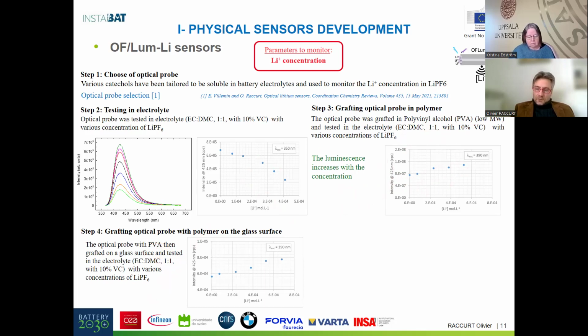It's not optical fibers, but glass surfaces, to check if after the covalent grafting of this probe to the glass, we maintain the variation of the luminescence as a function of the concentration of lithium ion, and it works. We tested it in the same electrolyte.